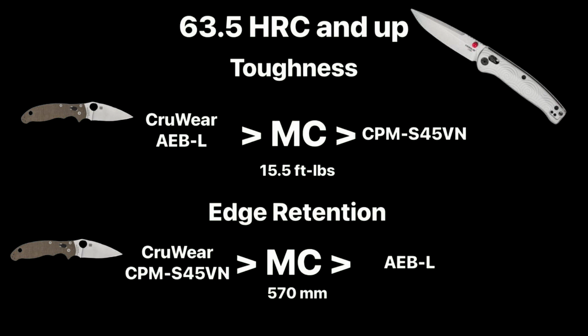But let's get a little bit into the details. At this hardness level, Cruwear and MagnaCut meet, their graphs intersect. They're almost identical in edge retention and in toughness. Where MagnaCut succeeds above and beyond Cruwear is corrosion resistance. At this level, MagnaCut is as corrosion resistant as CPM 20CV, M390, LC200N, and just slightly under H1. Cruwear and MagnaCut are both very sharpenable steels, which means manufacturers expend less energy and materials to finish them into the blades that you purchase.